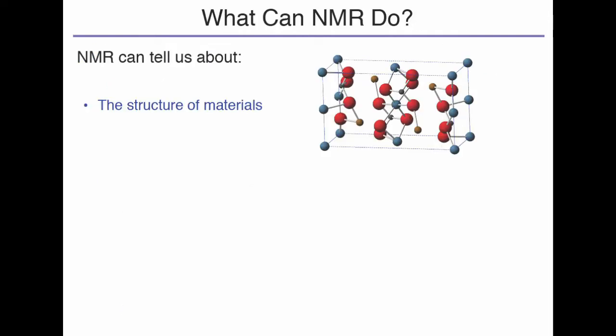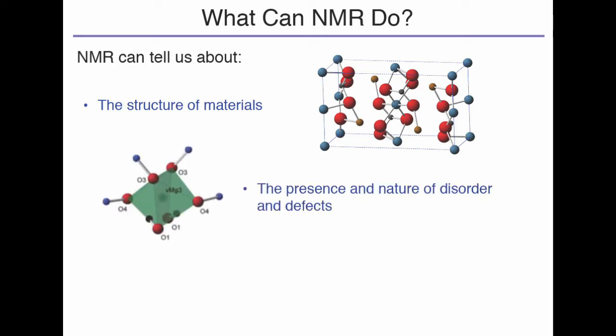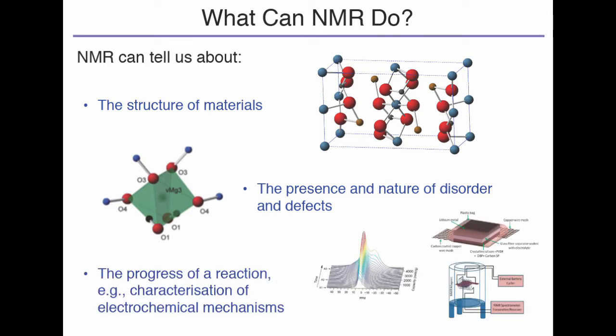So what can NMR actually do? NMR can tell us a lot about the structure of material. As I said, it's looking more locally at things rather than the long-range structure. But it can also tell us about the presence and nature of anything that's unusual. If you have any strange disordering or any unusual defects within that structure, where diffraction can't tell us, NMR can tell us a lot about that. In addition, you can do some in situ methods. You could choose to do NMR in situ whilst monitoring another type of reaction. You could do this for catalysis, or you could even do it for electrochemistry. You could cycle a battery while doing your NMR experiment and look at the electrochemical reaction occurring and link that to structure and changes that happen.